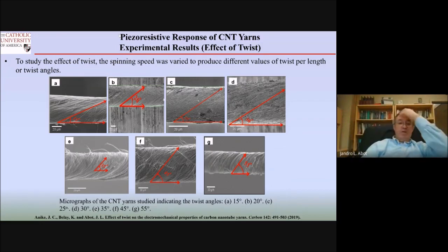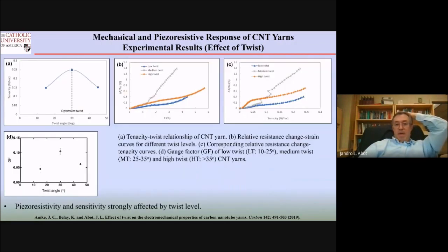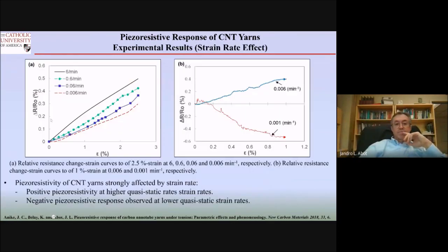So we had a study where we played with all of those parameters. What we found is that the best response is at 30 degrees, considering both the tenacity, which is load per unit weight and sometimes better than considering the stress of the material, and the gauge factor, which is the sensitivity. If you look at the slope of this curve, that's what we call the gauge factor. That's the sensitivity. You want a higher sensitivity. It's like any sensor: the higher the sensitivity, the better.